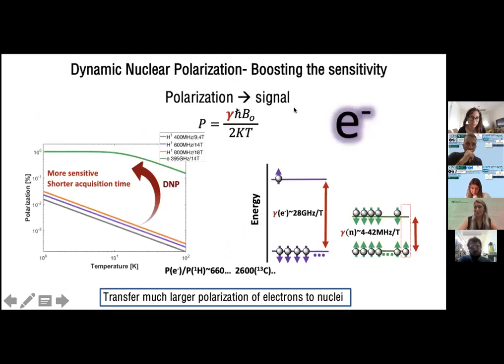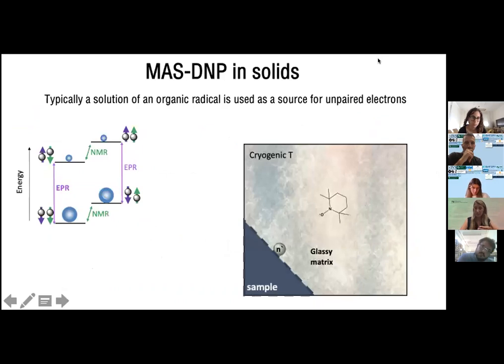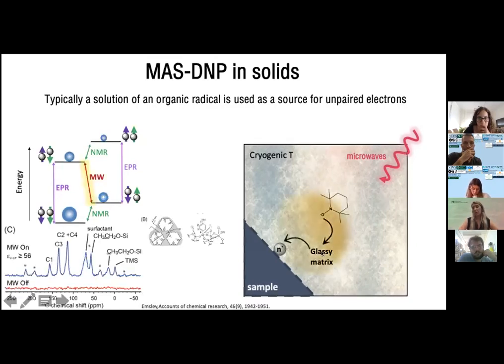In recent years, it's a very common technique to boost the sensitivity of NMR. We use electron spin polarization, whose magnetic moment is much larger than the nuclear one, and we transfer this polarization, which is proportional to the signal you can see in NMR, from the electrons to the nuclei. How do you practically do that? You have your sample with a nucleus that you want to detect. You need unpaired electron spin polarization. You add it as a solution of radicals in your sample. You irradiate with microwaves the transitions of the electrons, and the polarization transfers from the electrons through the solution to your nucleus, enhancing its signal.